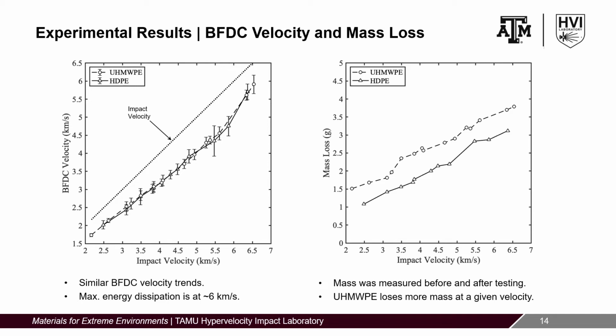The mass loss plots show that for a given impact velocity, ultra-high molecular weight polyethylene loses more mass than high-density polyethylene. The difference between the mass losses in the polyethylenes is likely a result of their distinct apparent failure modes. For example, the brittle behavior versus the ductile behavior. Ultra-high molecular weight polyethylene is more prone to fragmentation and fracture.